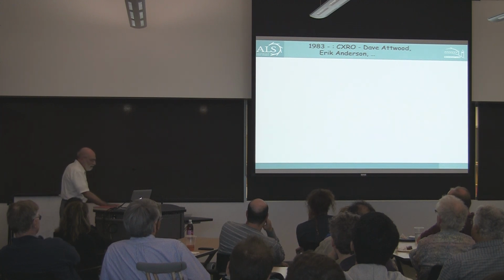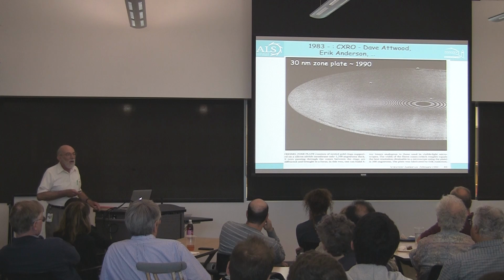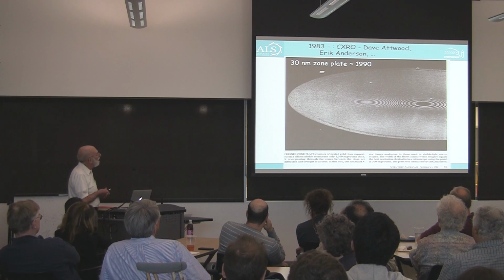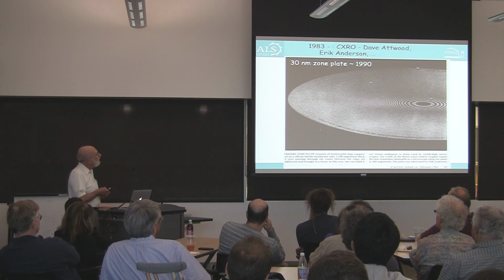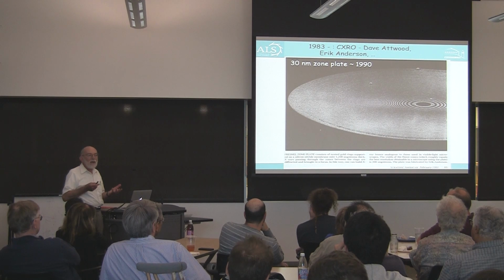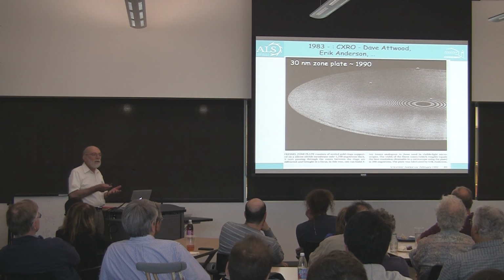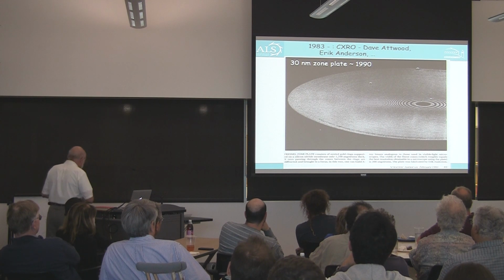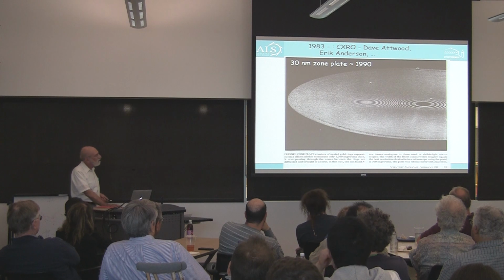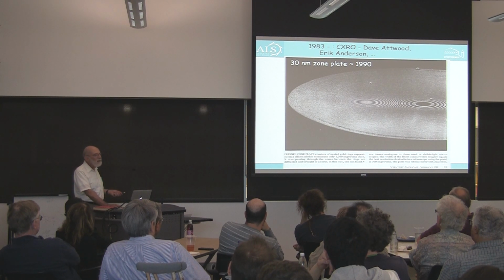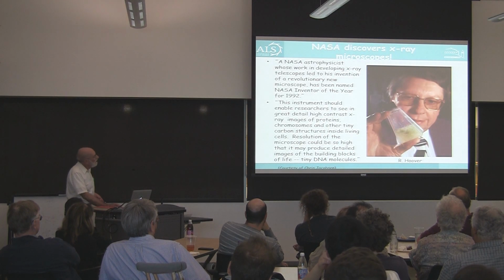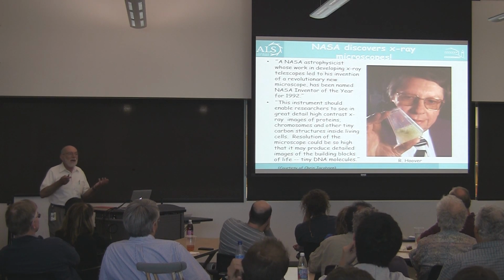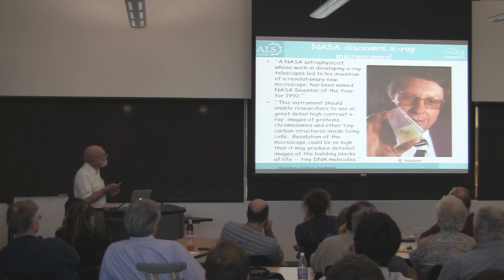Dave Atwood, in turn, recruited Eric Anderson, and the consequence of that was that well before the ALS was a working light source, Eric was able to make use of the nanowriter to build zone plates with 30 nanometer outer line widths, an order of magnitude better than what Günter Schmahl had been able to make by holographic techniques. And this is still the way to do it, and the Center for X-ray Optics is still the place for making zone plates. There were also, to give you another anecdote, other efforts.